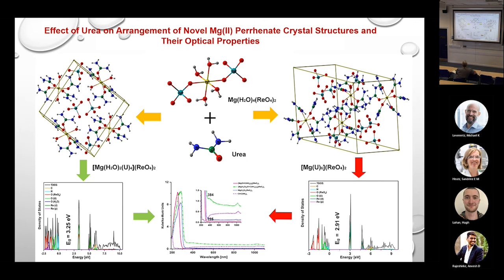This is when we consider the effect of urea on the arrangement of a novel magnesium perrhenate crystal structure and then its optical properties. We also simulate, model the crystal structure of three complexes where the number of urea increased, and find that this increase of urea is reflected in the optical properties, the absorption region extends, and we explain that this effect is due to the energy band gap decrease when the urea is 4 in the complex, and it decreases further when the number of urea ligands increases to 6 in the complex.